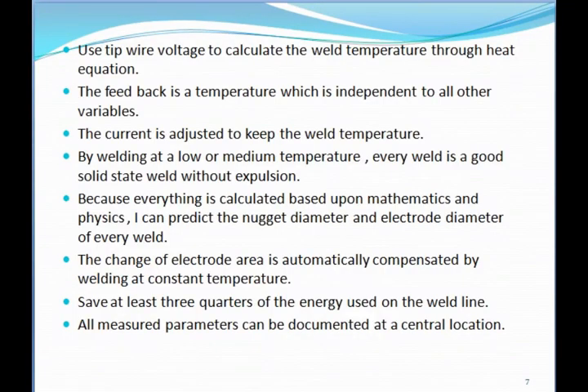Use the tip wire voltage to calculate the weld temperature through the heat equation. The feedback is a temperature which is independent of all other variables. The current is adjusted to keep the weld temperature. By welding at a low or medium temperature, every weld is a good solid-state weld without expulsion. Because everything is calculated based upon mathematics and physics, I can predict the nugget diameter and electrode diameter of every weld. The change of electrode area is automatically compensated by welding at constant temperature. Save at least 3/4 of the energy used on the weld line. All measured parameters can be documented at a central location.